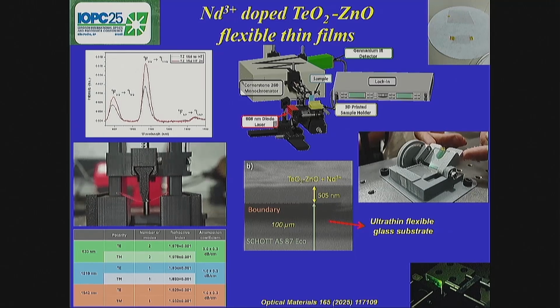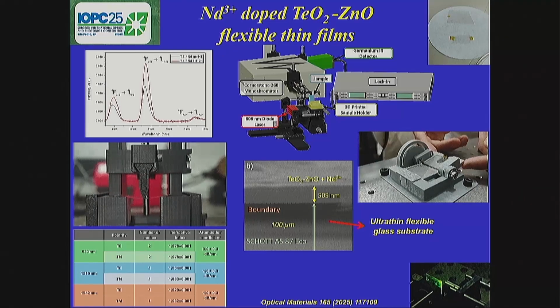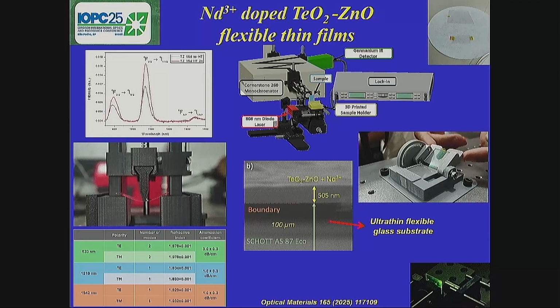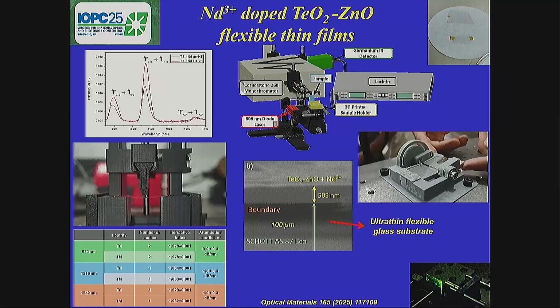Adhesion was very good with respect to the silicate flexible thin films. And a refractive index of about 2 could be measured in the visible and near-infrared regions, even using transverse electric and magnetic polarizations, which means absence of birefringence. That's very important for some optical devices.